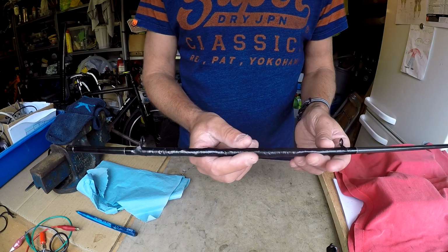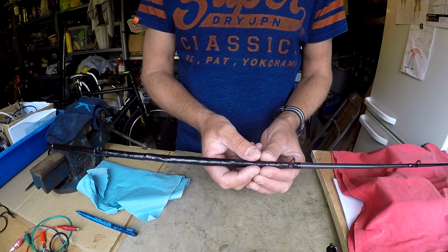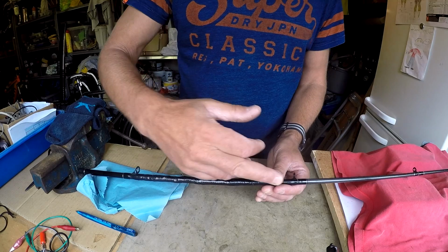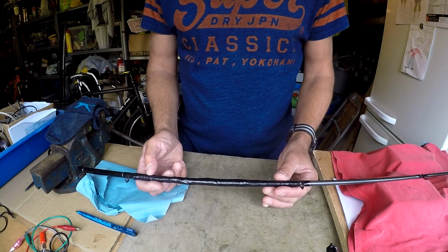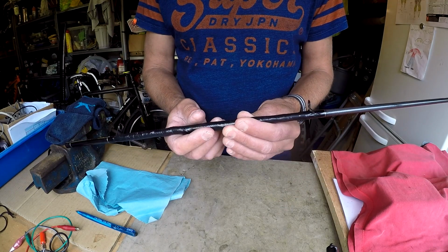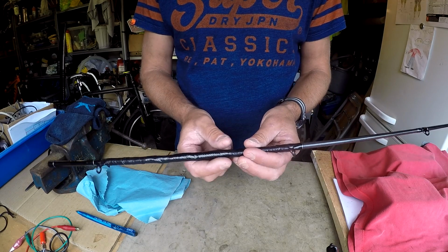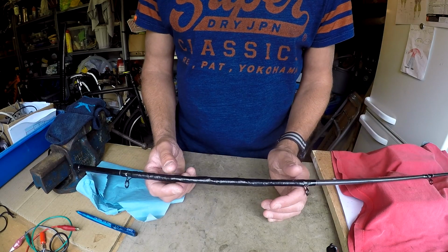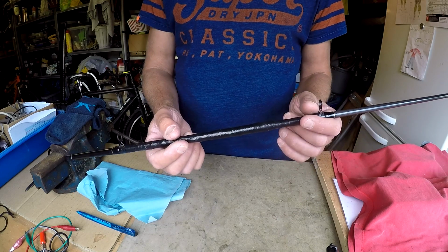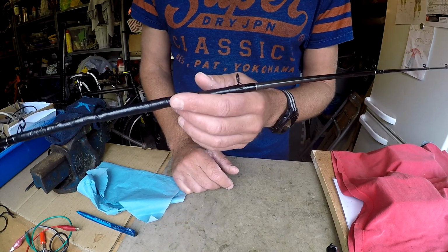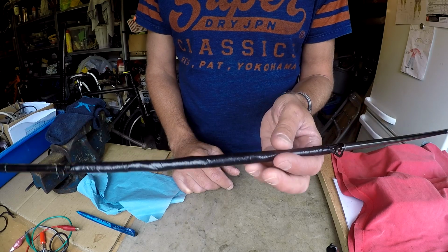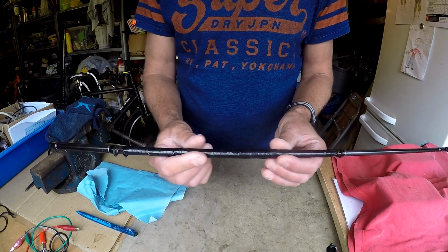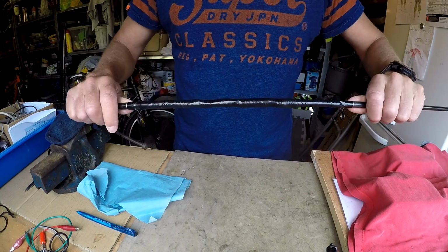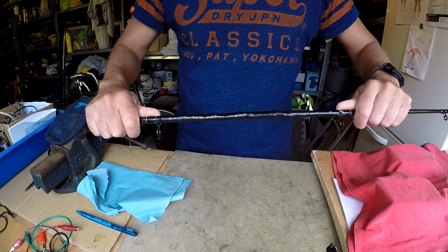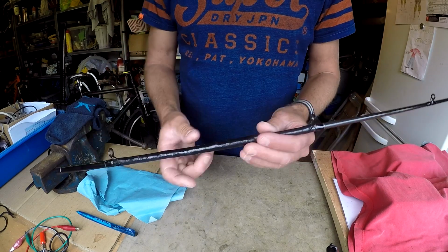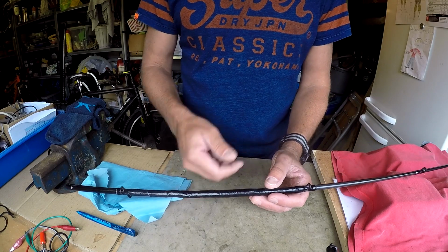But yeah, I let it go tacky, put it on, put another coat of epoxy on there, and then wrapped it in the tape. Well, I undid the tape about 3 or 4 hours ago, and it was still quite soft. It's not dry, but like I say, 18 hours, and total demold time is 30 hours. So I've retaped it up, pushed it down, but it's already quite rigid. So another 12 hours and I should be taking the tape off.